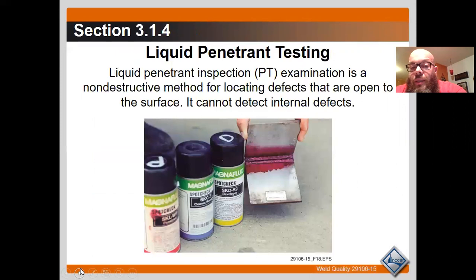Okay, liquid penetrant testing. I have some of this, and if I can find the part, I will bring it out and demonstrate this for you. Basically, liquid penetrant inspection is a non-destructive method for local defects that are open to the surface. It cannot detect internal defects, so it's for cracks. What you do is you spray a penetrant on there, which is the left can shown here. Then you spray a cleaner and wipe it down, so the only place penetrant would be is within a crack. Then you spray the developer on there. The developer turns the whole surface white, and where the actual crack is, it turns red, so that you can see exactly where a crack is or has occurred.